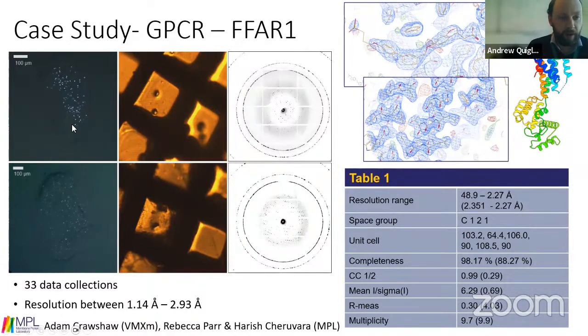I should also point out, to get these crystals onto these grids, the LCP, because it's like toothpaste, you can't just pipette it. So we're having to dissolve the LCP first of all using a low molecular weight PEG at high concentration or MPD, so that we can actually pipette these things. So it's possible that the MPD that we've used has led to the improvement in resolution.